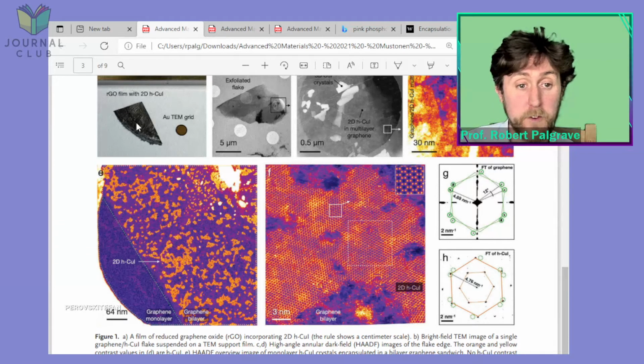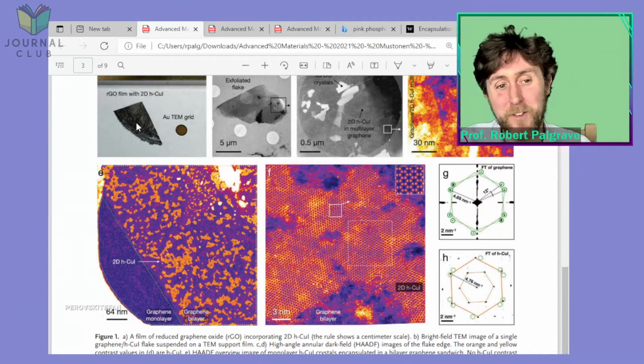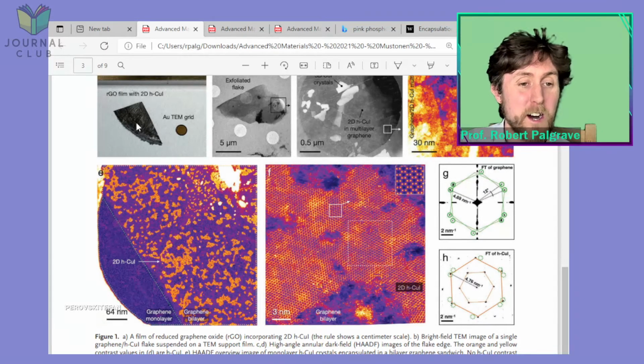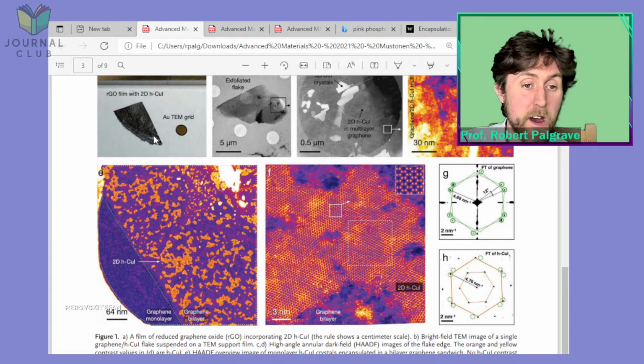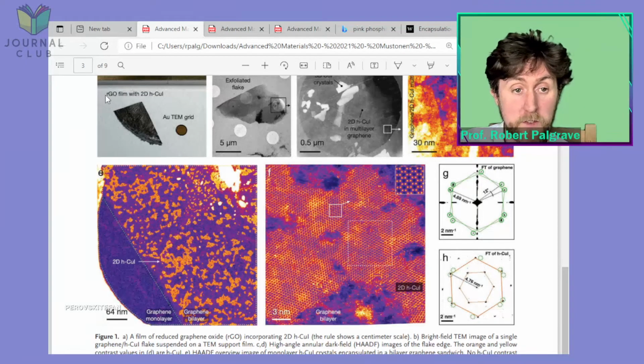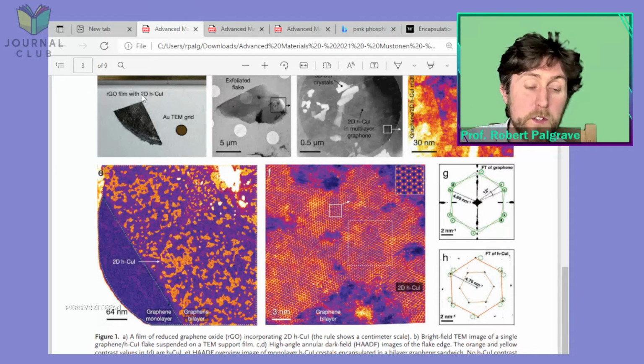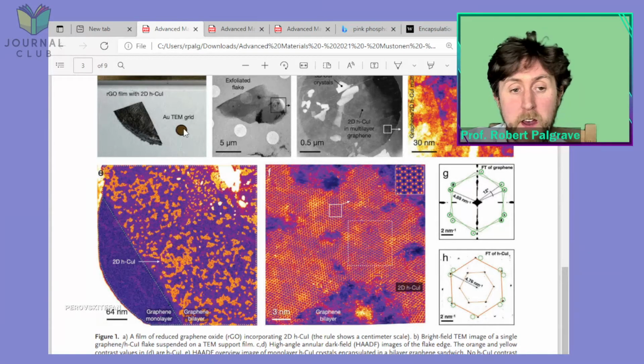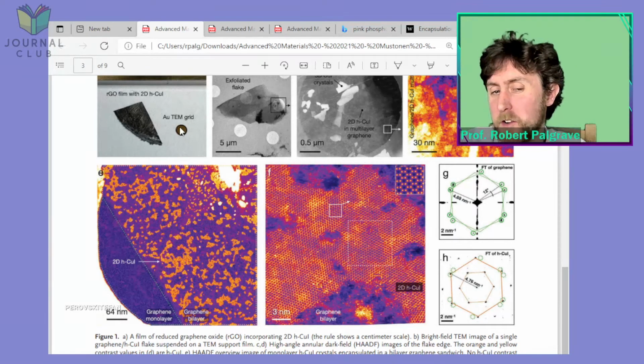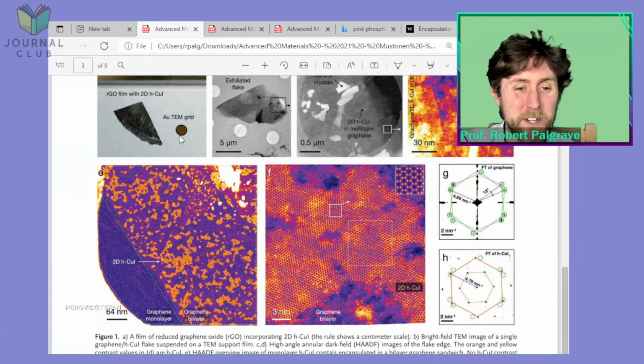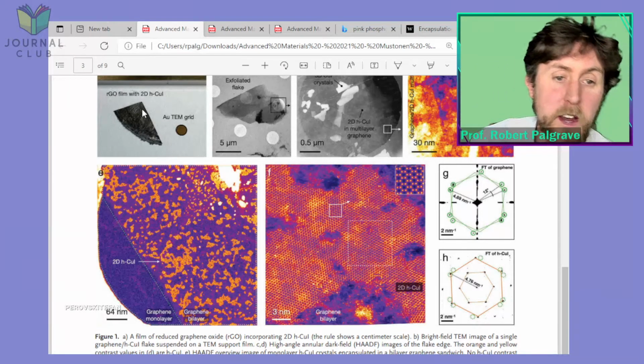I don't think people often just have a normal optical photograph that you might take with a smartphone camera these days, just of what their sample looks like. So this is their reduced graphene oxide film, or kind of graphene layers ready. We'll talk about reduced graphene oxide maybe in a minute, with the 2D layer of what they call hexagonal cuprous iodide in between it. Okay, so that's what the stuff actually looks like. There's a gold TEM grid. I don't really know why they put that there for scale. But if you don't know how big a gold TEM grid is anyway, that scale might not mean much to you. But it's probably a few millimeters wide, that TEM grid. They're pretty small. So we've got maybe 10 millimeters maximum, 1 centimeter, about the size of this flake here.